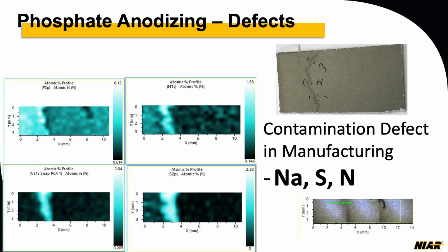In the image, you won't be able to see much, but there is a slight distribution of aluminum oxide as well on this. I've not shown that picture here because we didn't get a good image to show in the presentation. But at your center point where you have that defect, we have nitrogen, sulfur, and sodium. That's a definitive contamination. Sodium hydroxide is sometimes used for the etching process, and sulfuric acid also is used in the process. So while they were rinsing the part, I'm assuming that they have not cleaned it very thoroughly, and some must have been left behind, and that's where we are finding sodium, sulfur, and nitrogen. So this was a very good example of a defect for phosphate anodizing.